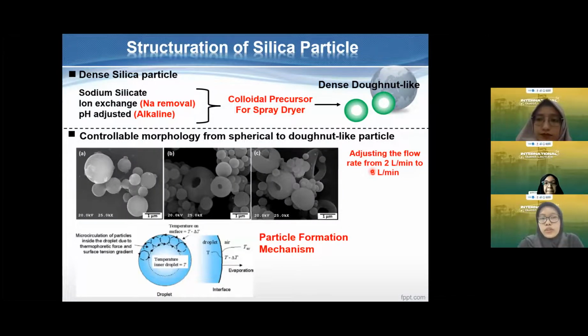Here I also change the... it is the same flow rate, but I use the other spray dryer method using the burner, using fire. It also has the same particles morphology. Also here, if we increase the flow rate, the donut-like particles are produced. And then if we increase until 6 liters per minute, the hole here becomes wider compared to the 2 liter per minute flow rate. Here we just get the spherical with dense morphology.